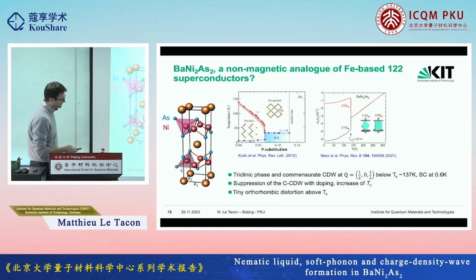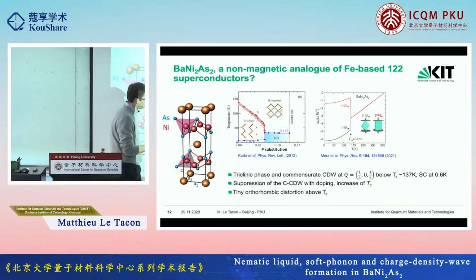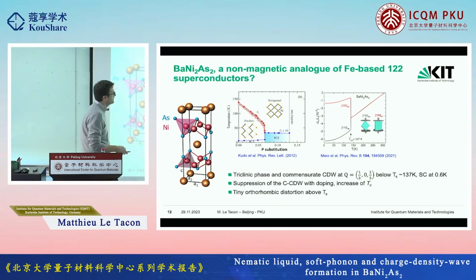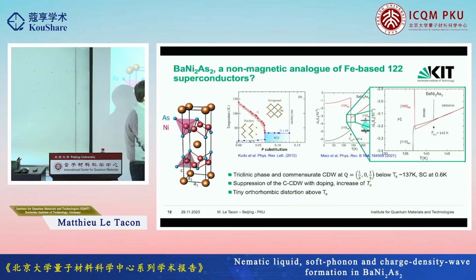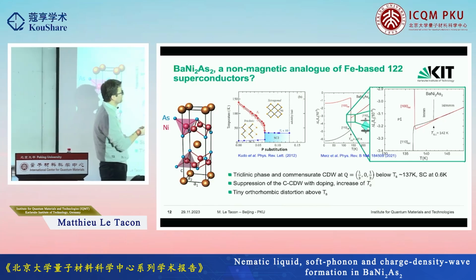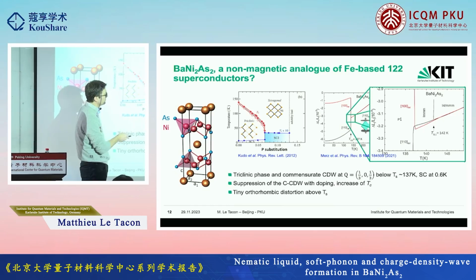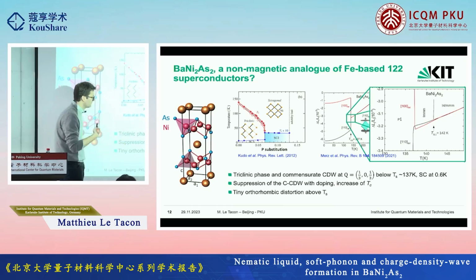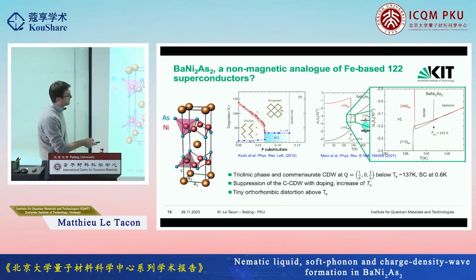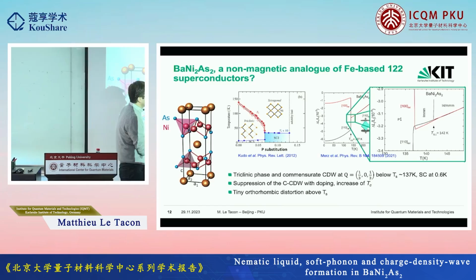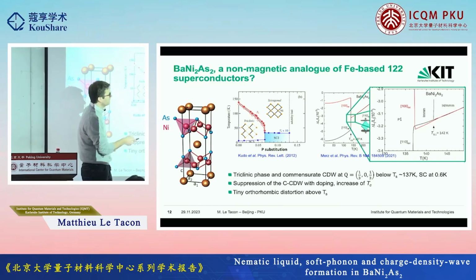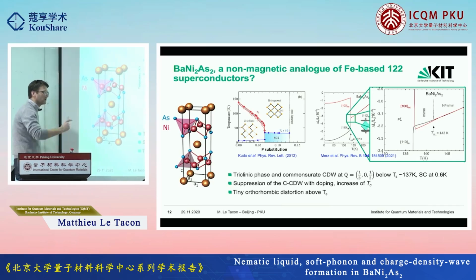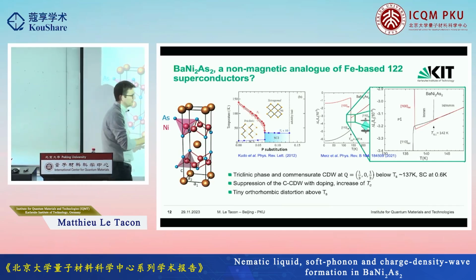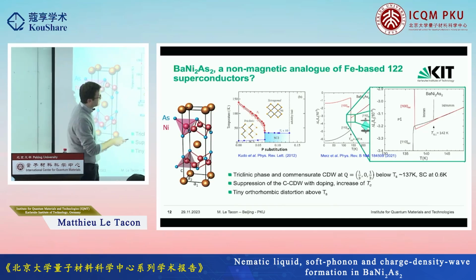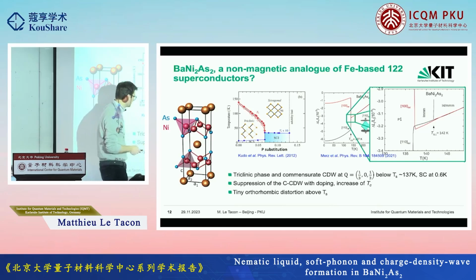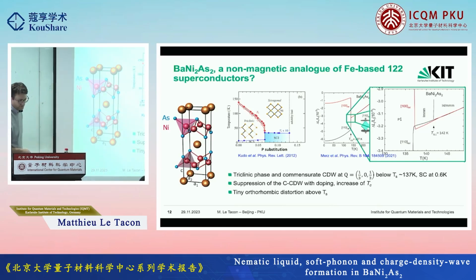But because we have this very high resolution in the dilatometry, if we look carefully at what happens just above, we can see that there's actually a small difference in the dilatation along the nickel-nickel bond and along the diagonal. It's a very small and very subtle effect, but it has been checked and cross-checked several times. The only way you can understand that is that you break the rotational symmetry going from an I4/mmm tetragonal phase to the Immm orthorhombic phase. In the iron-based superconductors it would be the Fmmm phase, so it's rotated 45 degrees. But as you can see, it's really at the limit of our dilatometer. It's very small, and there's a tiny orthorhombic distortion above the structural transition.